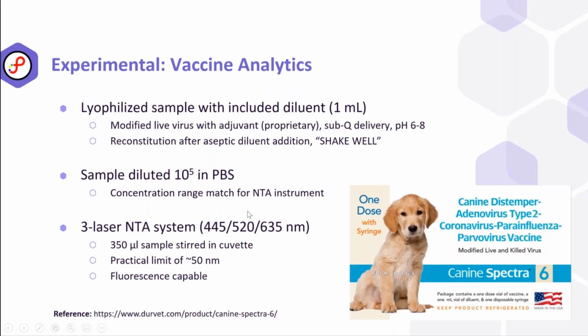But with the 445, that allows us to get down to a practical limit with a system like this of about 50 nanometers. And I raise that because I know I've seen specifications for other systems out there that'll say they can go down to 10 or 20 nanometers. And I think that we have to be a little bit careful there because some of that can be specsmanship. Practically speaking, in my lab, we had a single red laser system, and we spec'd that down to about 100 to 150 nanometers for biotherapeutics in general. So a little bit conservative on that, but I think that allows us to do better science and to understand things very well.